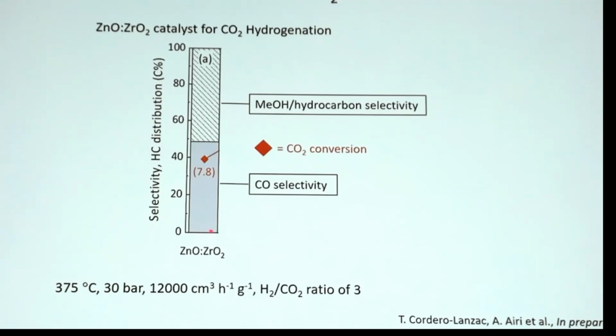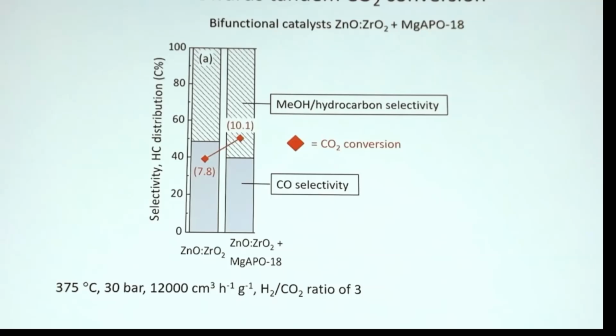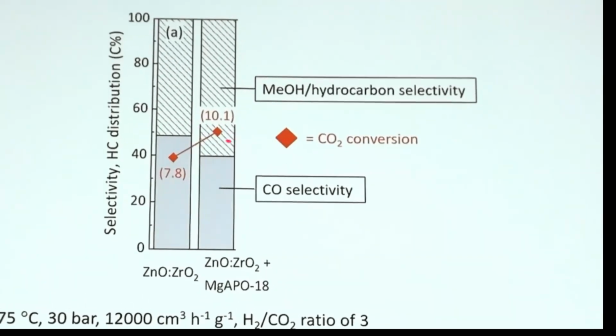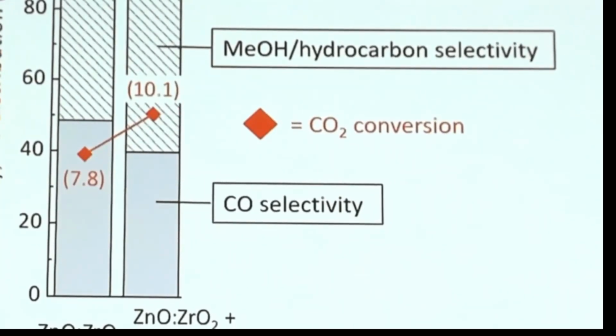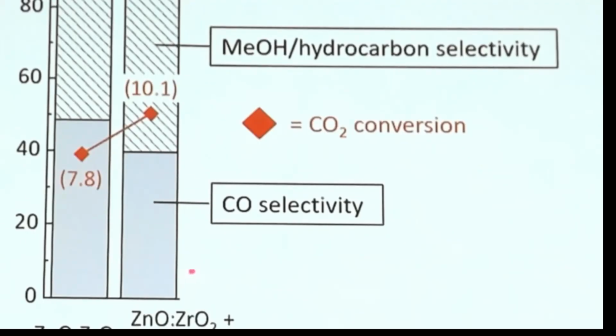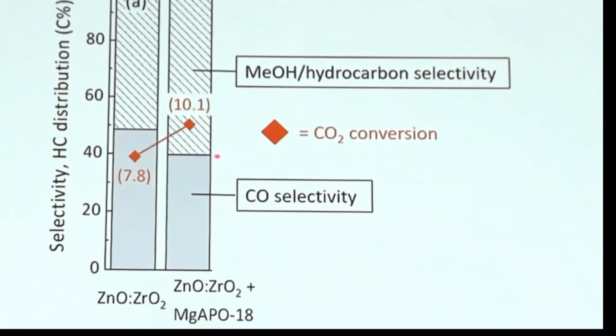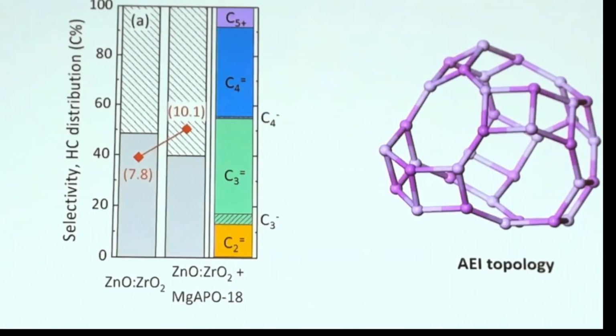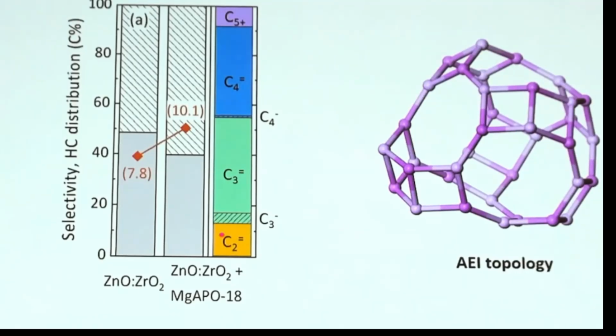So what happens now when we test this catalyst, the zinc zirconia, together with the MgAPO-18 catalyst? Well, first when we test alone, we have 7.8% conversion of CO2, about 50% selectivity to CO and about 50% selectivity to methanol. Then, when we mix it with the magnesium AlPO-18, the conversion is increasing, not enormously, but clearly showing that the further conversion to hydrocarbons is enhancing the equilibrium conversion. We have less CO selectivity, and the methanol and hydrocarbon selectivity is higher than the methanol selectivity was before. For the product distribution, we have mainly C3, followed by C4, C2, and C5, and the amount of hydrogenated products is very small.